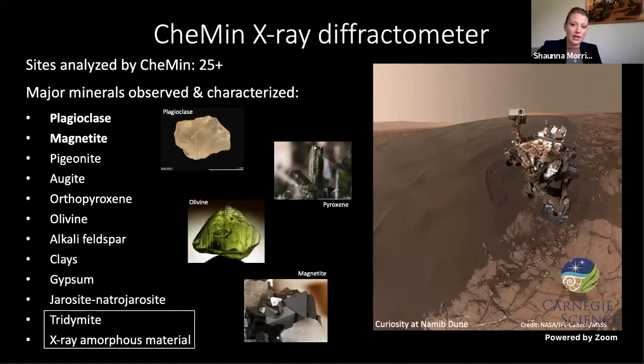And the second puzzling piece is the X-ray amorphous material. X-ray amorphous simply means that the material doesn't bounce X-rays in a regular way, like I showed you earlier. This can happen for two reasons. One is that the crystals are simply too small. They don't have enough long-range repeated order. And the other is that they are not crystalline at all, and instead their atoms are arranged randomly like you would have in a glass. We found that each sample that we've analyzed contains between 20 and 70% X-ray amorphous material. And this is very different from what we see in most rocks on Earth. So we're still working very hard to understand the nature and formation of these materials. And it's very likely that they're the product of weathering and alteration, but we can't be certain at this stage. This is where sample return would be incredibly useful.